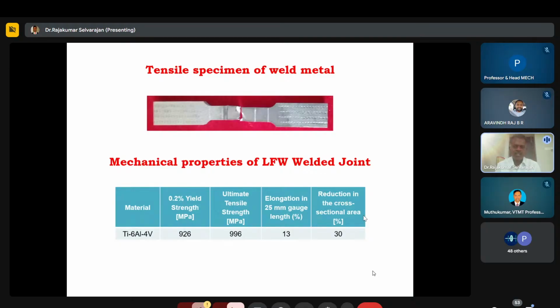We have to fabricate the tensile test coupons as per the ASTM standard, and then test them with the help of the UTM. You can see that the ultimate tensile strength of the titanium Ti-6Al-4V alloy has a maximum UTS of 996 megapascal, yield strength of 926 megapascal, elongation of 13%, and reduction in cross-sectional area of 30%. The specimen coupons are prepared as per the ASTM standard.